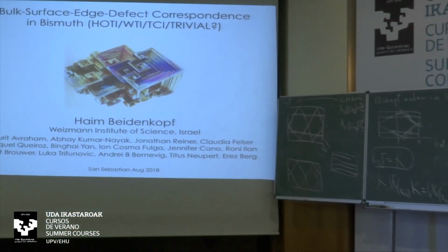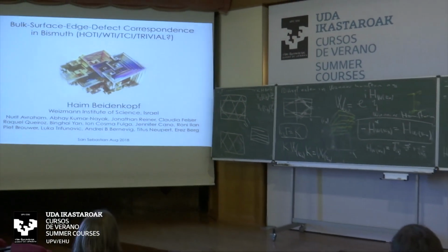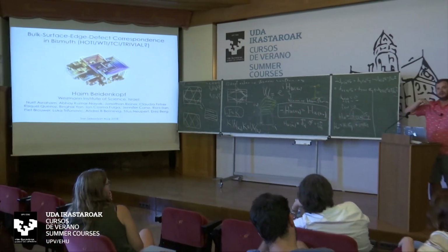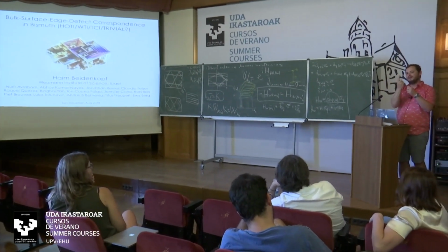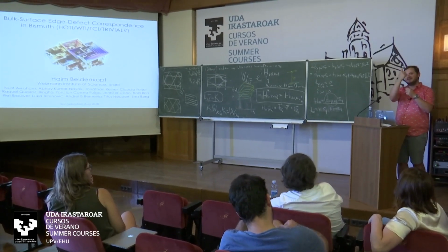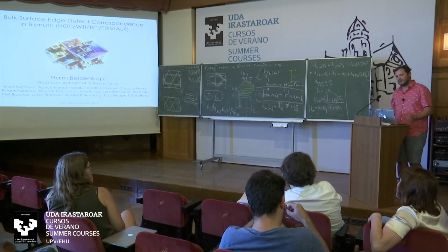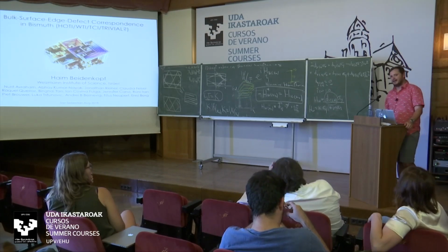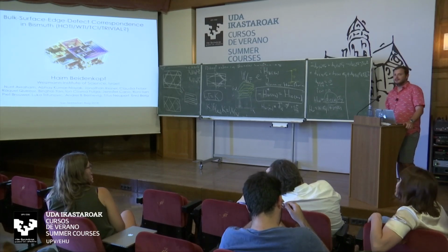So you can use it to induce growth. And mainly when the material is very anisotropic, then the atoms prefer to stick on the sides of the 2D films and they diffuse freely on the surface. But then if you have a screw, then you can seed perpendicular direction growth. So it's known for chemists, and they even sometimes use it as a method.